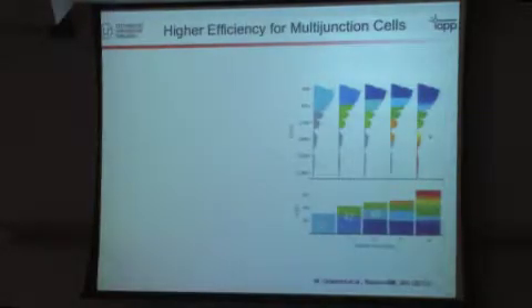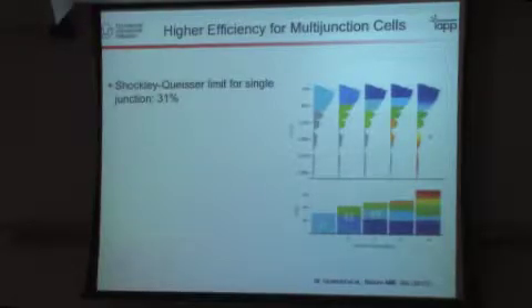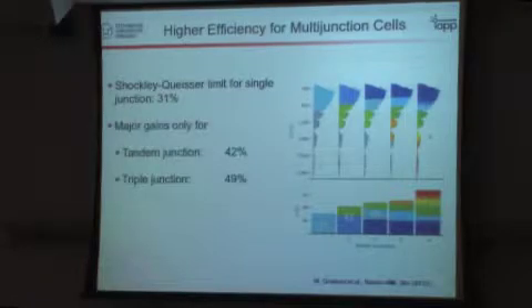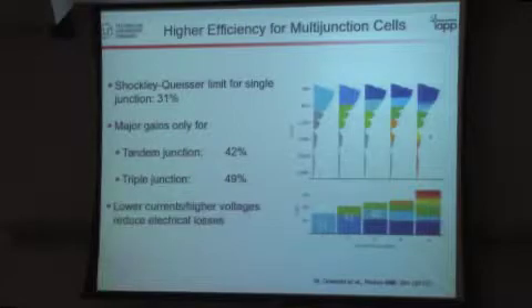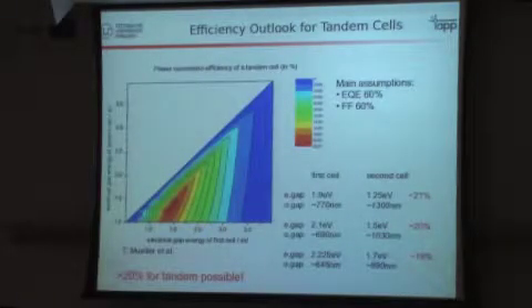And the way to go, like discussed recently in a paper by Michael Grätzel, is to harvest a larger part of the solar spectrum with several junctions, and you go then from the Shockley-Queisser limit of 31% for a single junction to 42 for tandem and for a triple to 49. And another point is that when you go to tandem or triple, you actually reduce the current, and therefore you have lower electrical losses. So we need to go to tandem or even to triple, and when you go to tandem, we did again some calculations, you find out that something like 20% is absolutely reasonable.